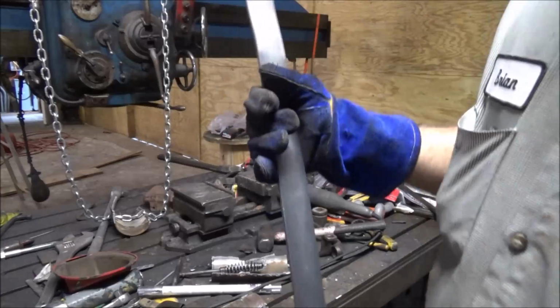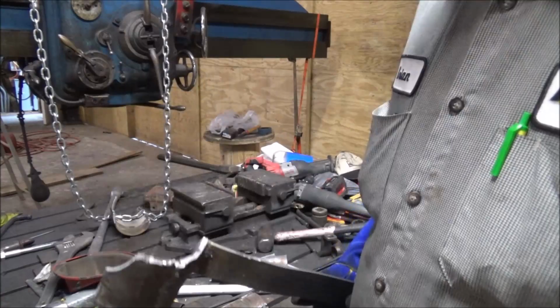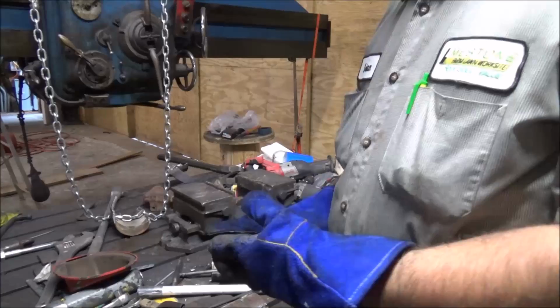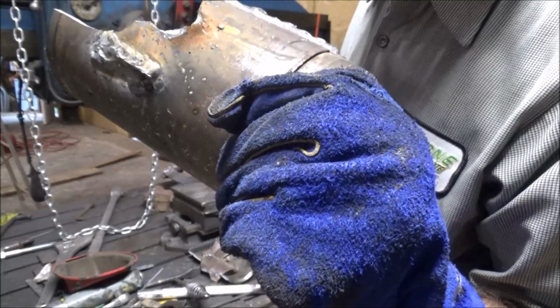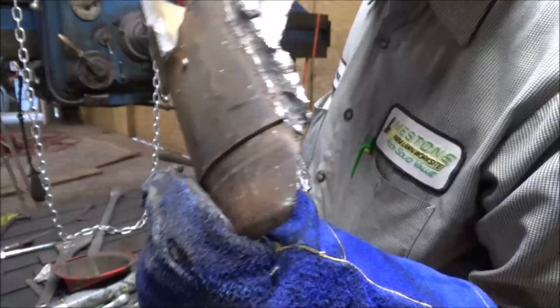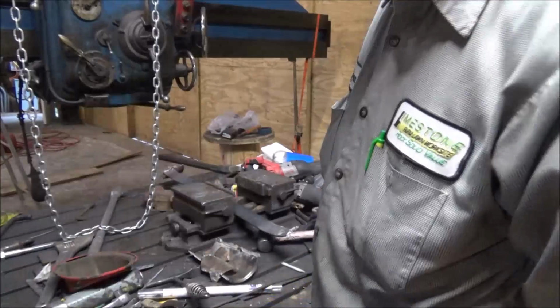7018, no shielding. Hot. Melt everything. It ripped the section where that weld was out of that. Pretty surprising. I welded that entire drill section on there and it held as good as that did. I wouldn't ever worry about it coming back off. Because for an inch of weld there, that took a lot of pounding to get that back loose. I think it took less to break the cylinder liner.